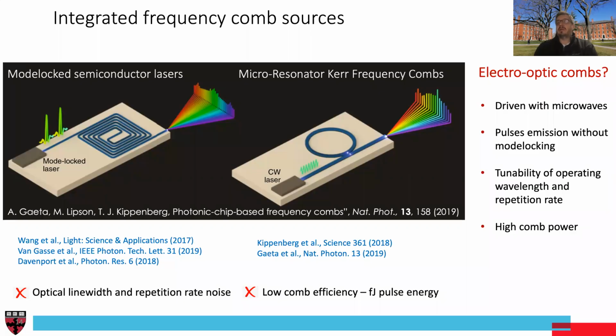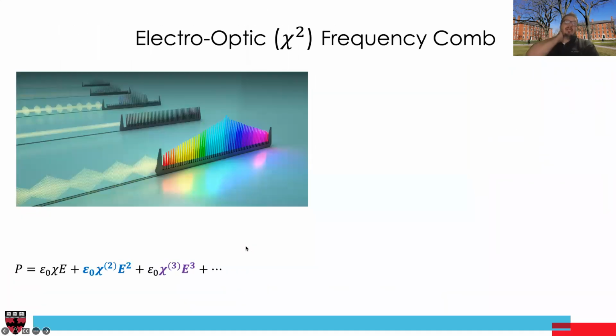And electro-optic combs basically take advantage, as I said, of this ability to modulate light very efficiently with very high speed in thin film lithium niobate modulators. Basically, we can carve pulses just by optical modulation. There is no mode locking that's required. There is no threshold. Basically, once we turn the RF source on, we get a comb. And as you will see, pump to comb efficiency can be very large, on the order of 20 to 30%. So next, I would like to discuss a few different electro-optic frequency combs we looked at.